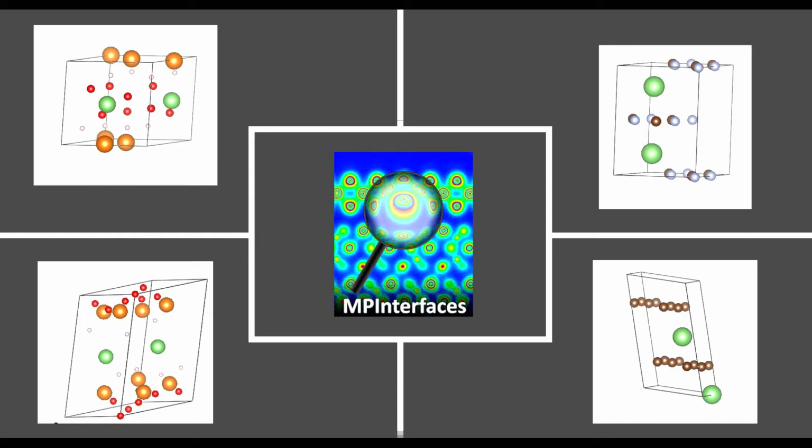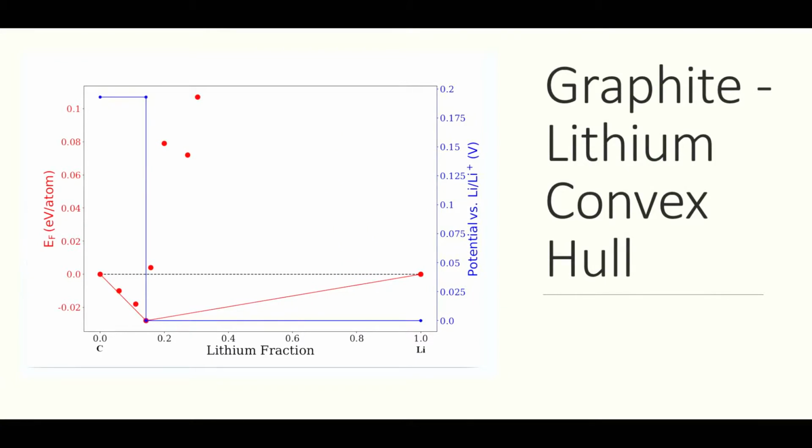Once lithium ions are inserted based off different percentages of lithium insertion, the structure can then be relaxed using DFT to find the ground state energy. This ground state energy can be compared to the base layer material energy and the lithium ion energy. This comparison can then create a convex hull, which is used to find the thermodynamically ground state phases of the lithium ion compound at any of its compositions.